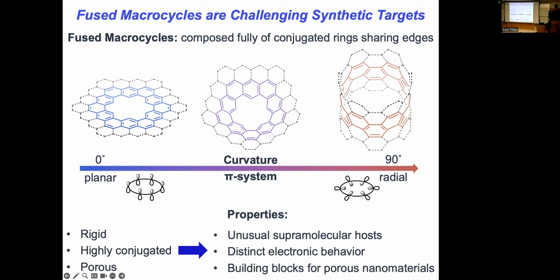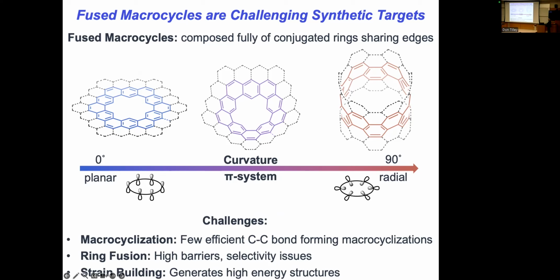And there are a number of them that you could consider, you know, flat ones like this that are related to kekulene and structures like that, or maybe somewhat bent ones, all the way over to nanobelts like this. So there's a continuum of curvature that takes us from one kind to the other. All of these are based on fused rings. And once you start to curve, then you're going to introduce some strain. By the time you get to a nanobelt, that's a lot of strain, right? So these should have unusual properties in terms of host-guest chemistry, interesting electronic behavior. They're porous, so interesting maybe as building blocks. And so lots of reasons to try to target them.